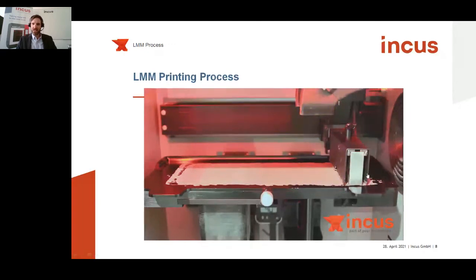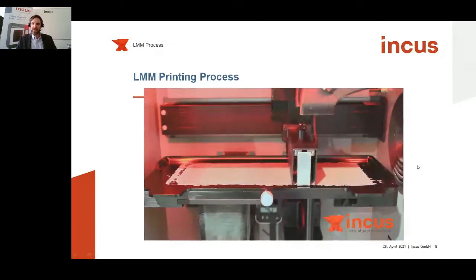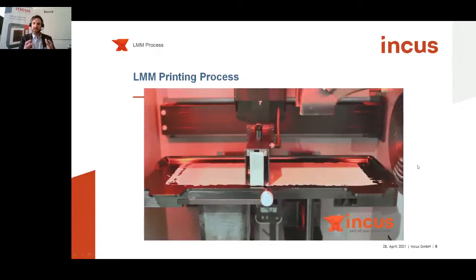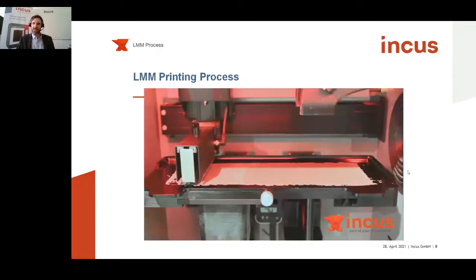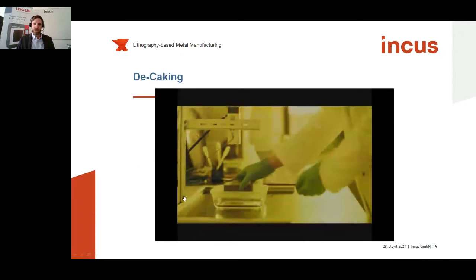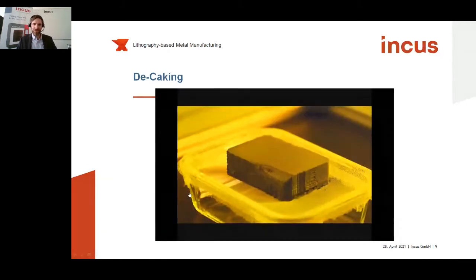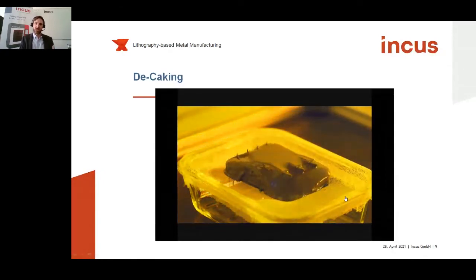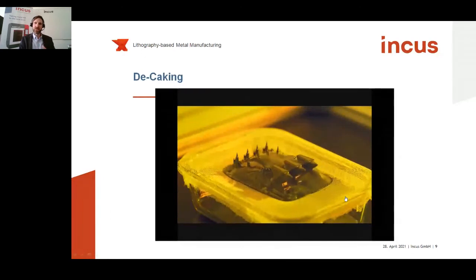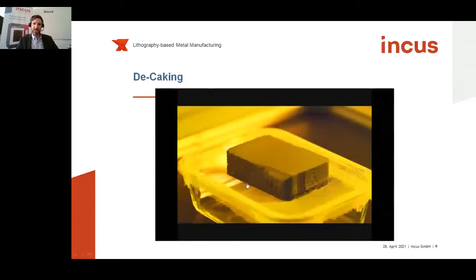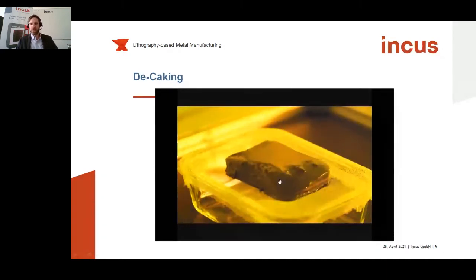So as you can imagine, after the 3D printing procedure, the green parts are all submerged in this block of material. So the second thing I mentioned was the decaking process, and this looks like the following. That's my favorite processing step in this whole production chain. It's the melting of the feedstock block, and you see here that the material melts, and the green parts, which are solidified by the blue light, can be extracted. So I'll let it run once more so you see what's actually happening. So at around 30 or 40 degrees Celsius, the butter-like feedstock melts, and only the printed green parts stay behind.